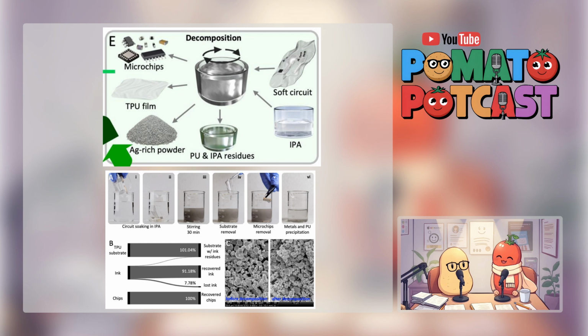That's fantastic. How much of the ink do they get back? They reported recovering about 91% of the ink material this way. Pretty good recovery. And the TPU substrate can be cleaned and reused directly. Same for the microchips, assuming they weren't damaged. They could potentially be reused too. And the silver in the dissolved ink? You wash the recovered silver flakes with more IPA. That gets rid of the dissolved polyurethane residue.